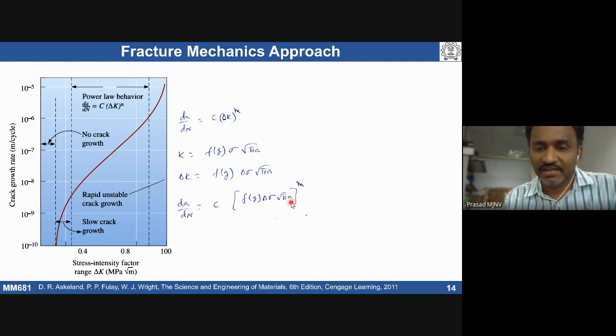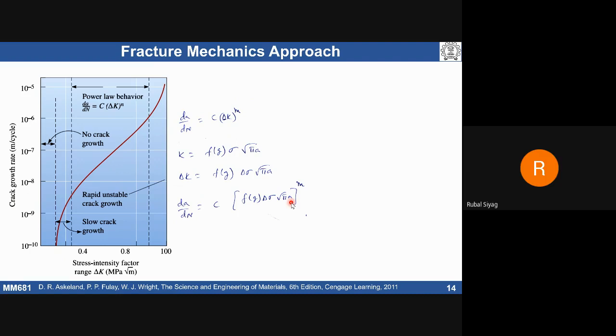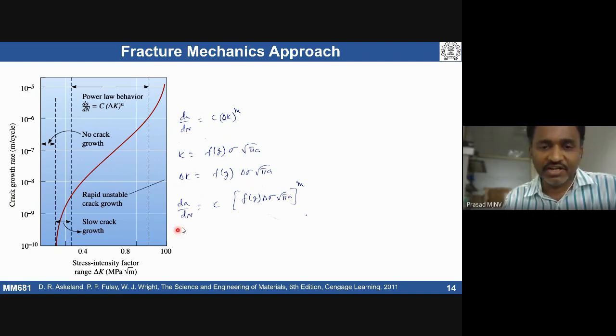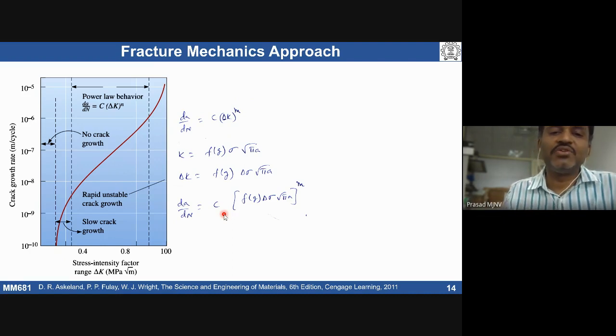Because there is A here and there is A here, you need to integrate. Take the dN to that side, bring this one here, and integrate it. I can get how many cycles are required for the crack to propagate from a certain length to another length, or the other way around. Given this many cycles, if I increase the number of cycles to this much, how much is my crack length going to change?